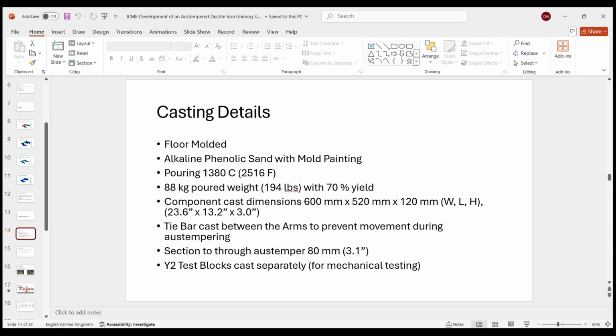And obviously the other thing you have to do is prove out the casting. The most common way you prove out the casting is with separately cast test blocks. Now, although the casting section itself has a maximum of 80 millimeters, most of the forces and loads and issues they're concerned with are actually on the arms. And the arms are of the thinner section. So it was decided to cast Y2 blocks, which have a section of only 25 millimeters. So we weren't looking at the actual results in an 80 millimeter section, which would have been a Y4 block. We decided to just look at a Y2 block.